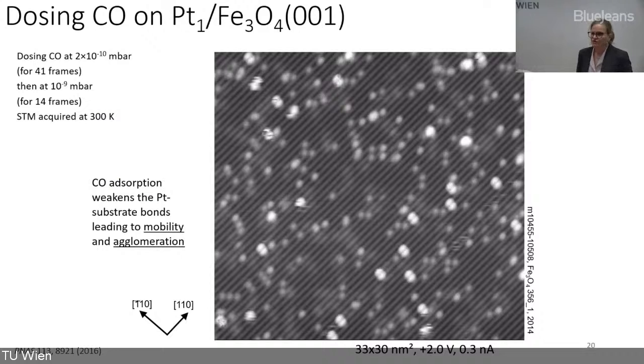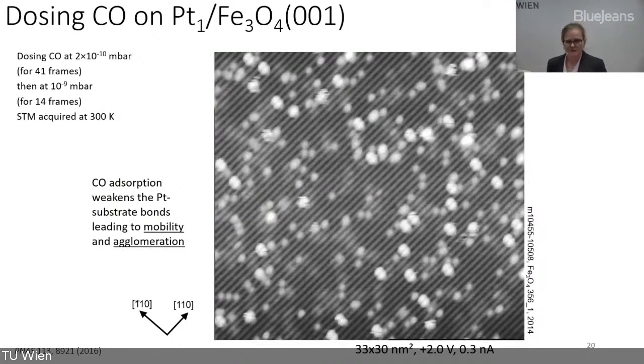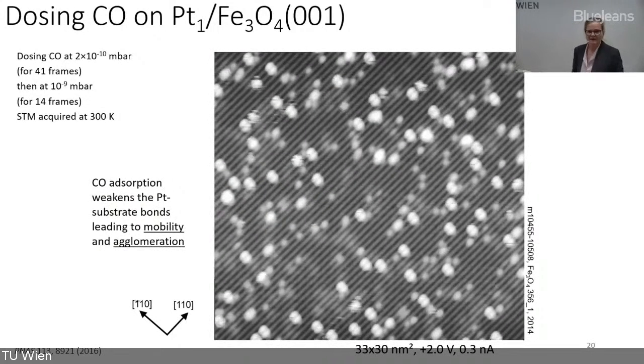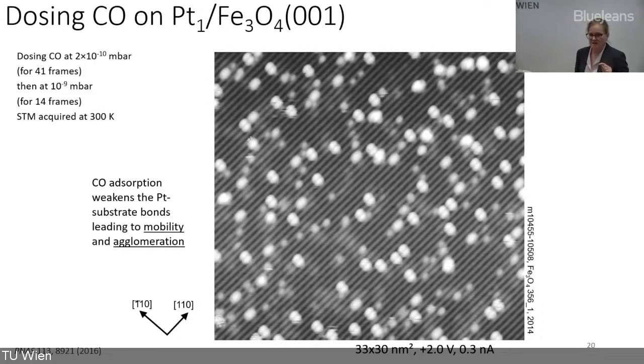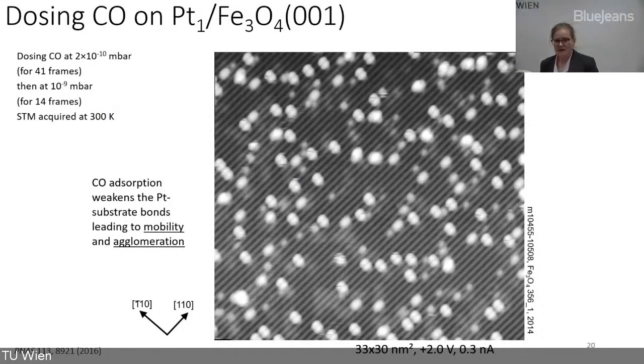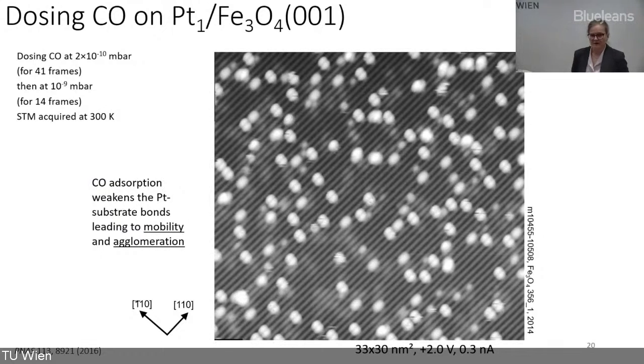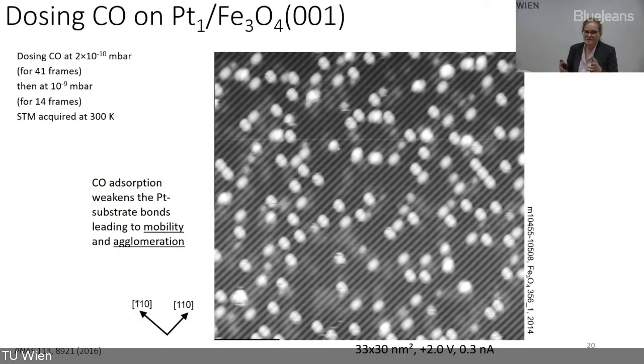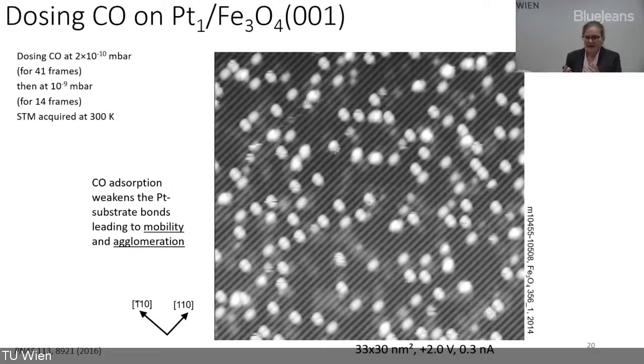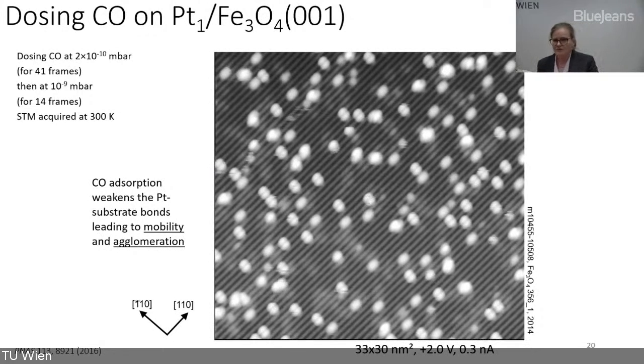I want to show what happens when you open a valve on your ultra-high vacuum chamber and leak a little bit of carbon monoxide in. You see some mobility, and then many of these double-lobe features that I explained a minute ago start to appear. So clearly the CO adsorbs, comes to the platinum, and lifts it out a little bit, so it will also start to move around.